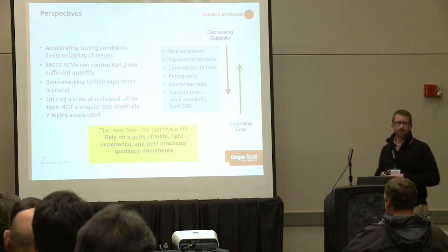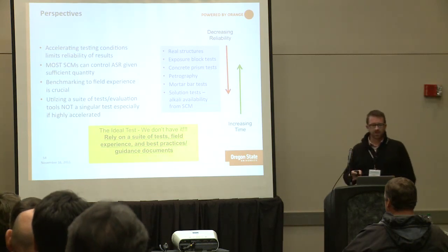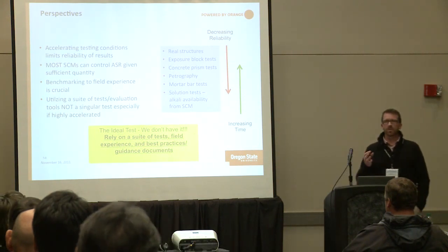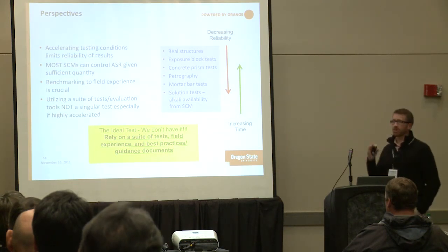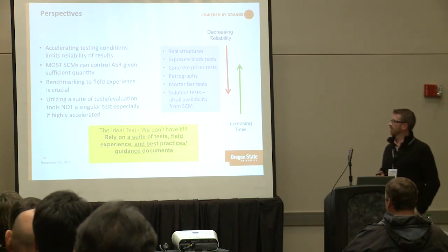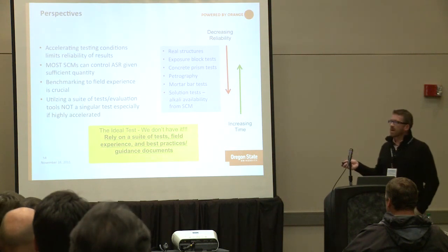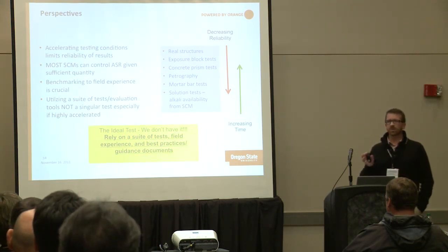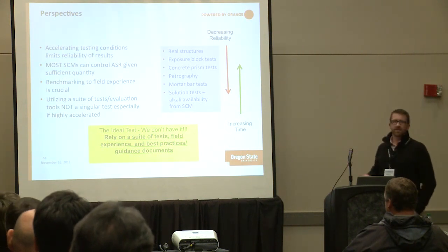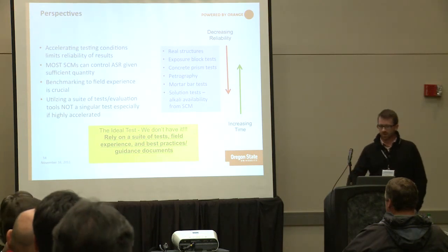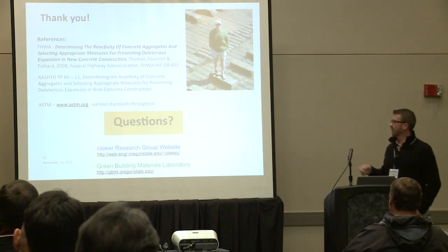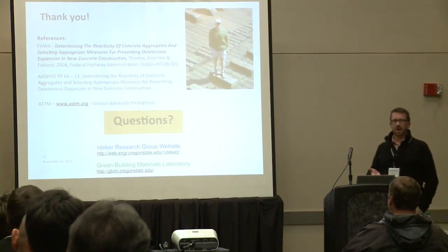To wrap up with a few perspectives: accelerating testing conditions certainly limits the reliability of results. Most SCMs can control ASR provided they are used in sufficient quantity — ternary blends or combinations may provide benefit at lower levels without impacting constructability. Benchmarking to field performance is crucial, and utilizing multiple pieces of information is critical — not just one singular test method. Using field performance records, information from a petrographer, and multiple test methods in combination gives a better snapshot. We don't have the ideal test method yet, but hopefully we can get there soon.